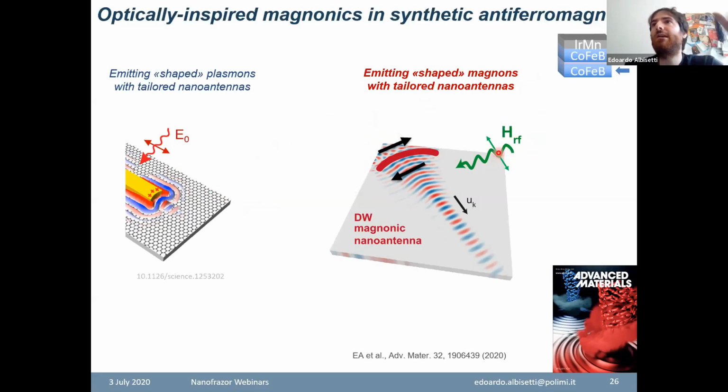And if we illuminate, let's say, the whole chip with a uniform and, let's say, not highly localized oscillating magnetic field in the gigahertz range, then this field actually happens to couple very well only with the structure that we wrote via tam-SPL, so with the domain wall, and sets this spin texture in oscillation. And the oscillation of the spin texture is what actually emits spin waves.